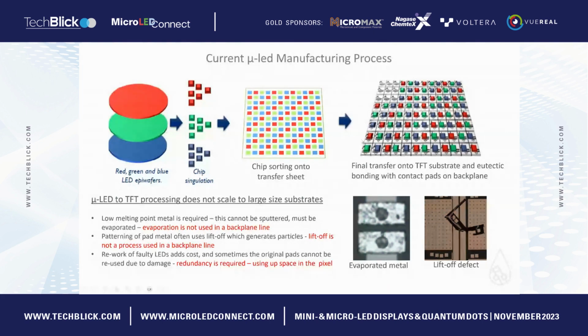So this is probably one of the most challenging parts of the process, is that you have to create an ohmic contact between the pads on the backplane and the pads on the LEDs. And for that, typically people will use low melting point metals to form a eutectic bond between the pad on the LED and the pad on the backplane. And these might be materials which are processed in kind of thicknesses of 2 to 3 microns, and therefore have to be patterned by processes like liftoff.